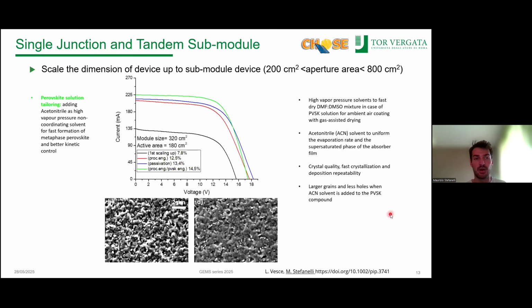The last step of our optimization, in this case for the wide bandgap perovskite, was the perovskite solution tailoring. We added a certain amount of acetonitrile to our DMF-DMSO solution mixture in order to have a high vapor pressure non-coordinating solvent for the fast formation of the mesophase of the perovskite.